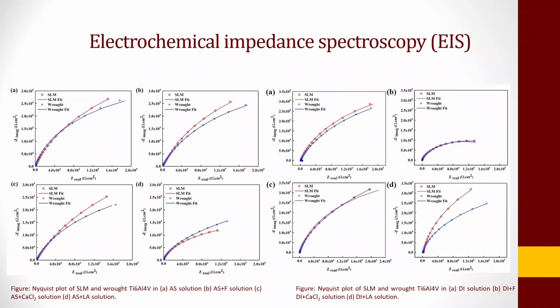So here are the detailed electrochemical impedance spectroscopy data. It's kind of a mix. You could see, for example, in graph A, that the semicircle was initially lower, but once you go to slightly higher frequencies, the semicircle gets bigger for the additively manufactured sample as compared to the ROT. However, in B and C, you could clearly see that SLM is behaving better at all frequencies. However, in some others, like D on the left, you could see that ROT is behaving better.